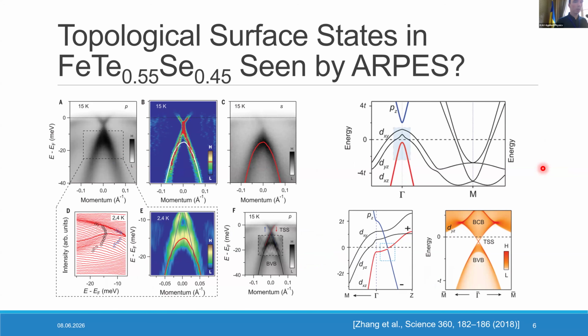There were multiple works showing a bit contradicting results, but the main issue with it was the energy scale and correct interpretation of data, because it's quite tricky again, even though it happens along the gamma-Z cut in the Brillouin zone, which, as has been mentioned before, is not deformed much by ARPES when you go far away from the center of the Brillouin zone. You still get it almost ideal as it is, but the interpretation was quite different.